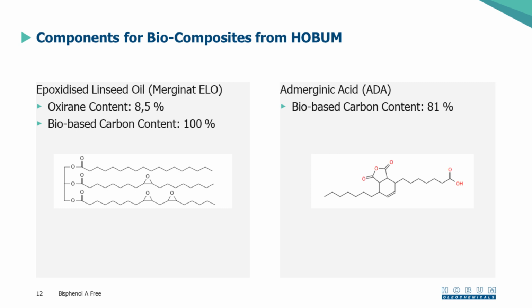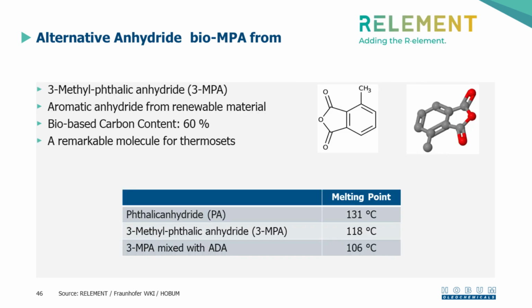And the other component that is also quite interesting is Admerginic acid that you see on the right side. It's a Diels-Alder product out of isomerized Admerginic acid, a conjugated C18:2 acid that has a Diels-Alder reaction with maleic anhydride to yield this anhydride. So it's in principle a molecule that can react at 3 points. We have 3 acid groups that can react with the oxirane rings.